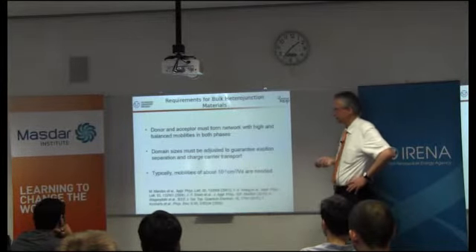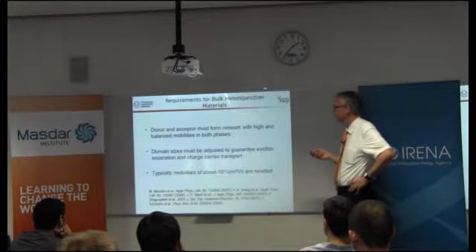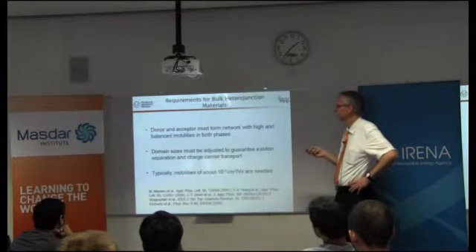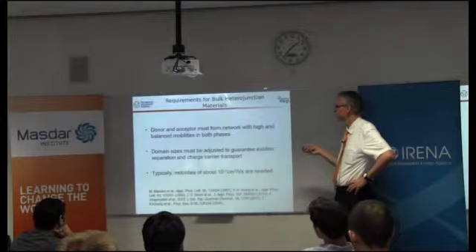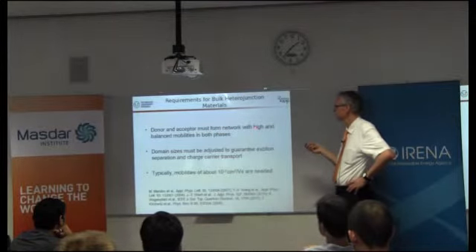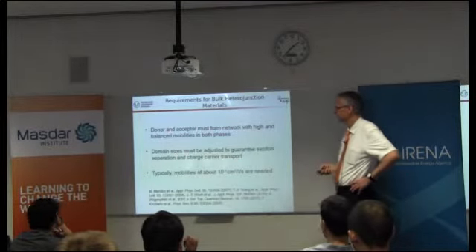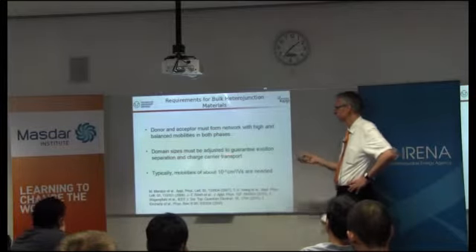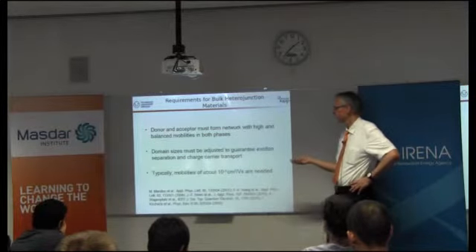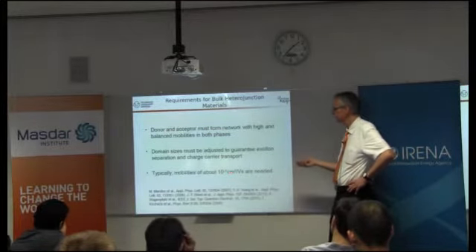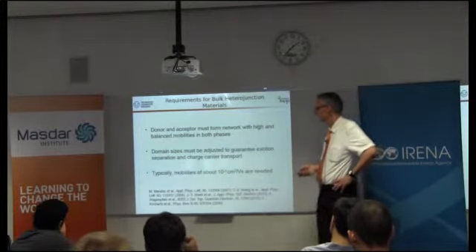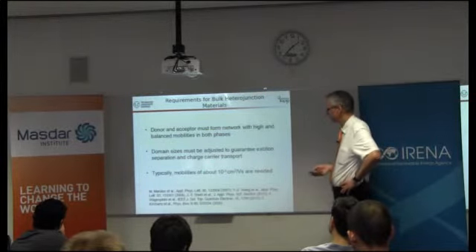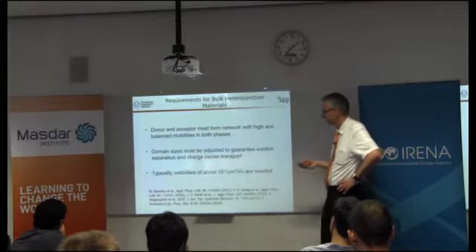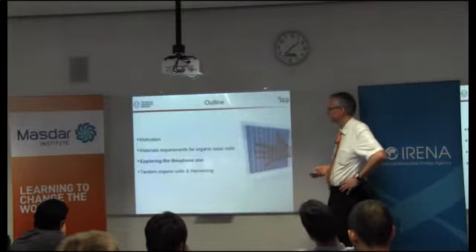Now, that leads to the point that the requirements for the materials are complicated. We need materials which form such a network which can transport carriers very well. We need to adjust the domain sizes. And at least for organic materials, we need fairly high mobilities. 10 to the minus 3 is already a quite high mobility for a disordered organic material.